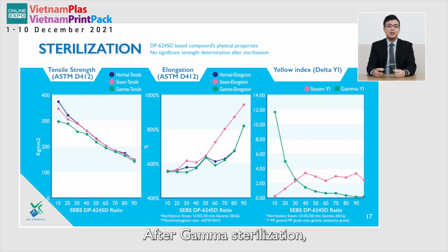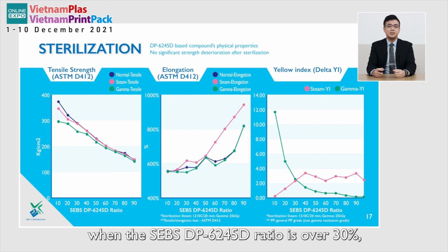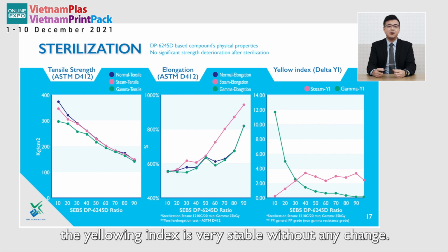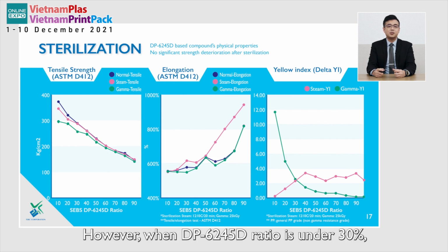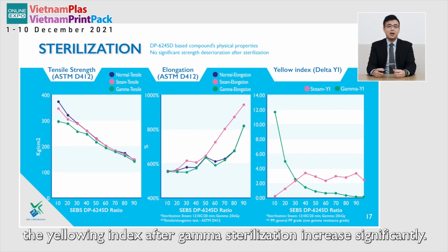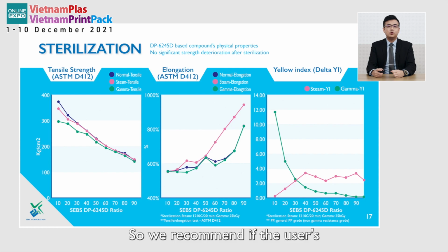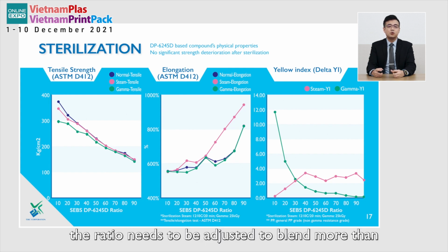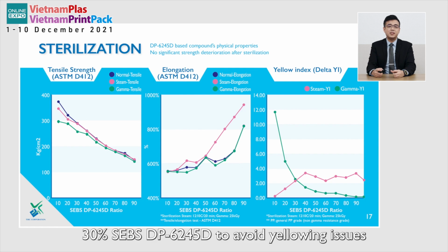After gamma sterilization, when the SEBS DP6245D ratio is over 30%, the yellowing index is very stable without any change. However, when the DP6245D ratio is under 30%, the yellowing index after gamma sterilization increases significantly. So we recommend, if users' sterilization equipment is gamma radiation, the ratio needs to be adjusted to blend more than 30% SEBS DP6245D to avoid yellowing issues.